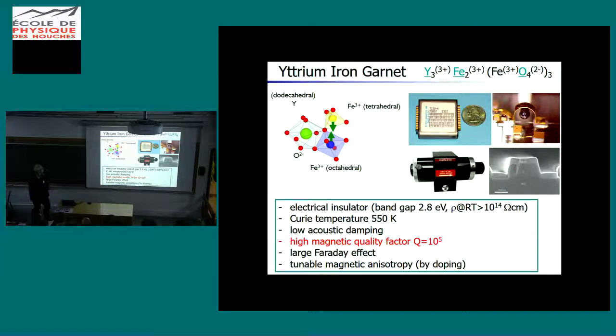These octahedral and tetrahedral irons have a magnetic moment of spin 5/2. They are strongly antiferromagnetically coupled. But you have more of the tetrahedral than the octahedral, so the whole system is magnetic. It's a ferrimagnet. So yttrium iron garnet is a very nice material. It's basically the best ferromagnet there is, if you count it in terms of the magnetic quality factor of the magnetization dynamics. It has many real applications because of that.